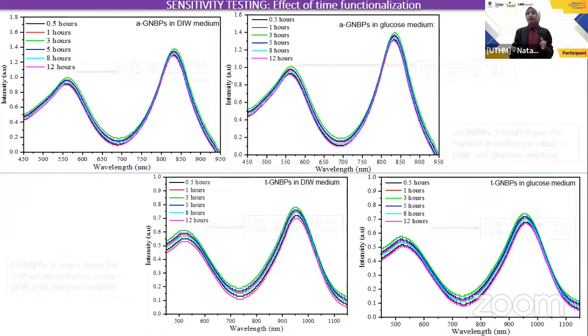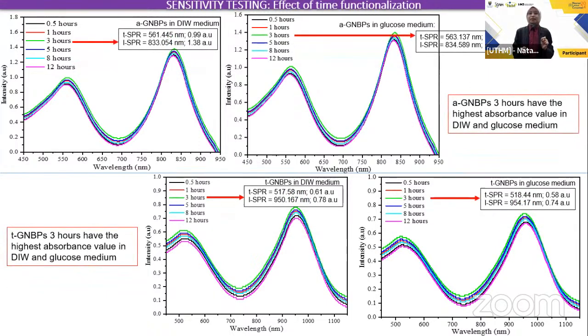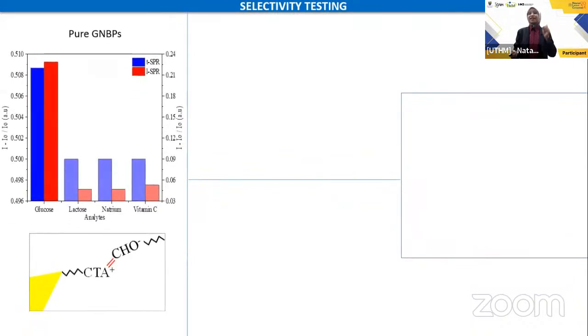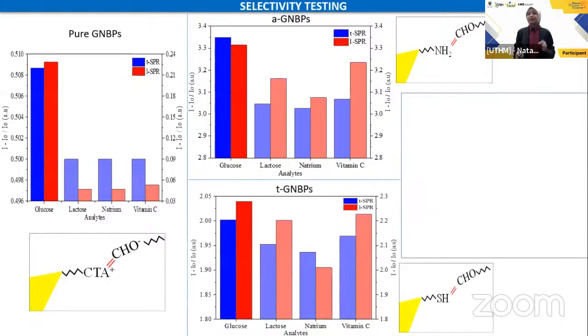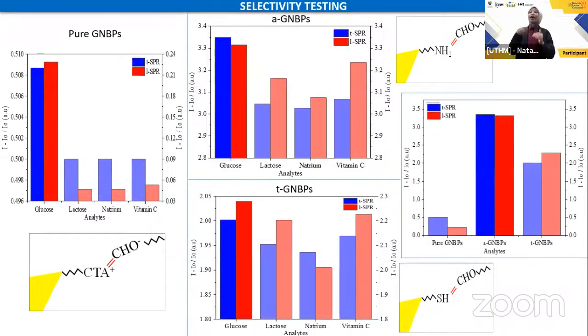Based on this result, 3 hours of A-GNBPS and T-GNBPS has the strongest signal response compared to the others, denoted by the highest intensity value. These conditions also correspond with the characterization results, where 3 hours has the highest absolute value and the highest surface density value. Okay, ladies and gentlemen, we also have the selectivity performance of the plasmonic sensor when detecting glucose molecules using pure GNBPS, A-GNBPS, and the last one, T-GNBPS, as sensing material. Basically, A-GNBPS and T-GNBPS perform a higher selectivity response compared to pure GNBPS, with A-GNBPS having the best selectivity response.